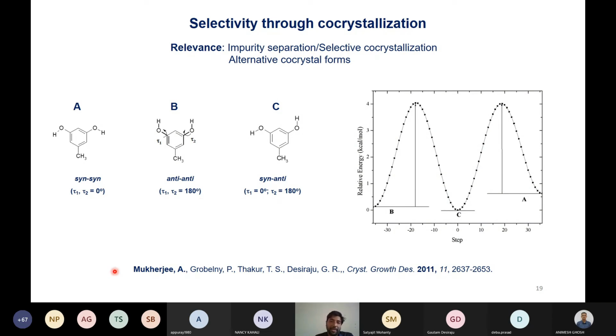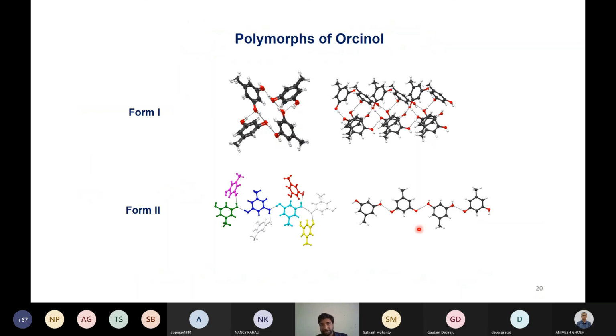So here what we have taken as a model compound is orcinol, which has degrees of freedom in its functional group. It's a resorcinol, 5-methyl resorcinol, and you can see this tau 1, tau 2, and there are 3 possibilities of conformational polymorphs. If you look at the energy scan here, A, B, C, the differences are very small, but there is a certain difference in these conformational energies. So we tried to look at whether we can discriminate these conformers through co-crystallization.